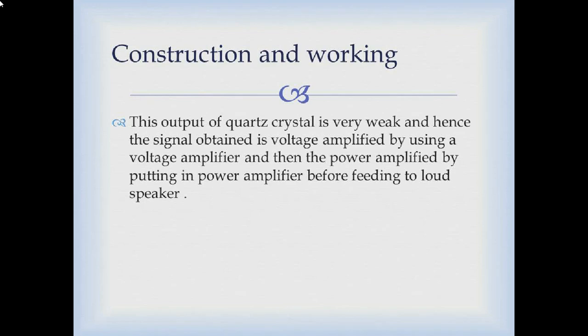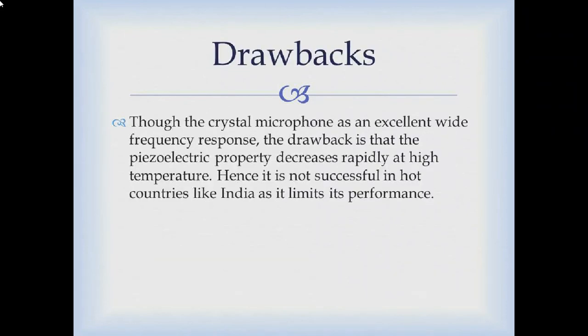The signal is first voltage-amplified using a voltage amplifier and then power-amplified using a power amplifier before feeding to the loudspeaker. Although the crystal microphone has an excellent wide frequency response, its drawback is that the piezoelectric property changes with temperature. At high temperatures around 100 degrees Celsius, the piezoelectric property decreases rapidly. Hence it is not successful in hot countries like India, where temperatures can reach around 50 degrees Celsius — this is the biggest drawback of the crystal microphone.